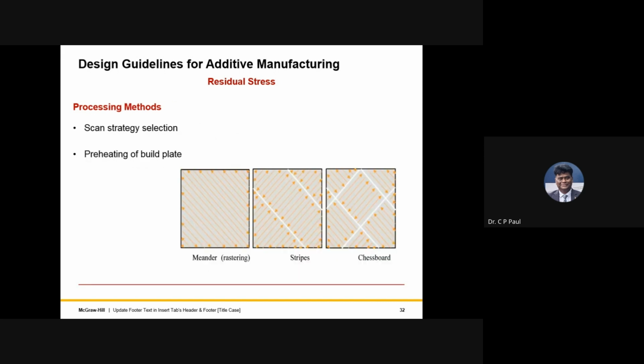When we talk of the residual stresses, we need to think of the different processing methods. For example, you can use meander and rastering. You can also involve stripe, like two stripes filling, and you can have chessboard. And in these, whatever we are talking about, every layer, every rastering pattern, is rotated by 67 degrees, and this is possible whether it is stripe, chessboard, or meander.